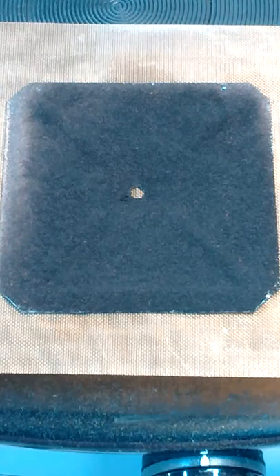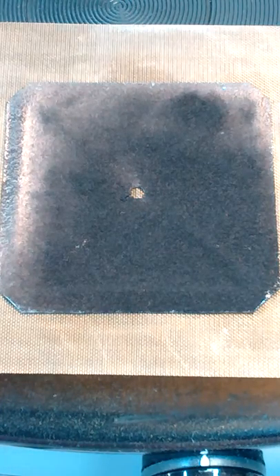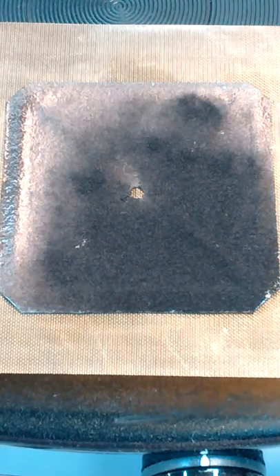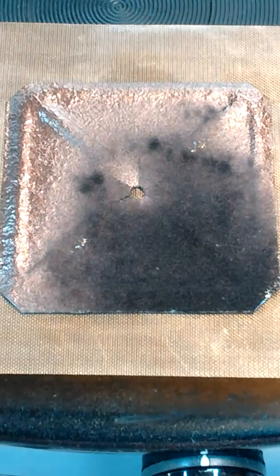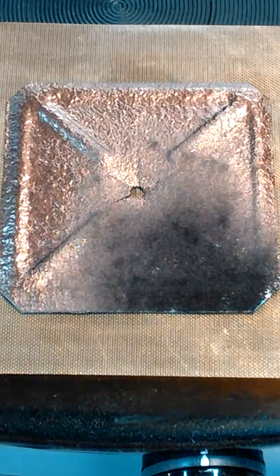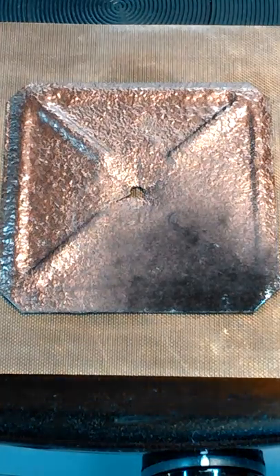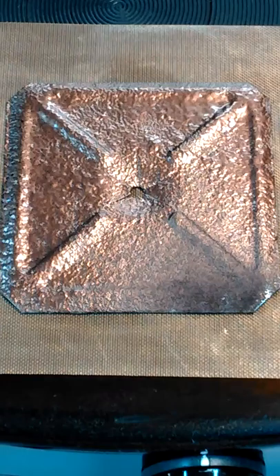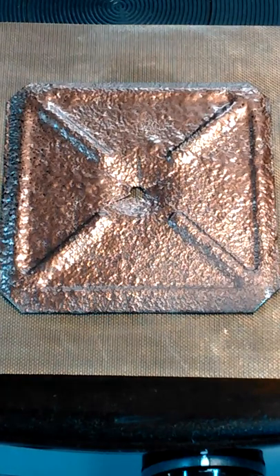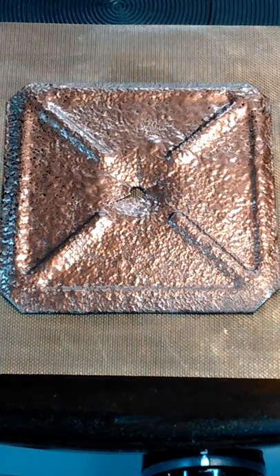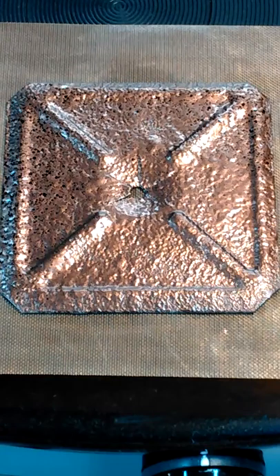And there it's started. So far from beginning to end, a minute and 30 seconds. Full cure is approximately 10 minutes at 350 to 400 degrees.